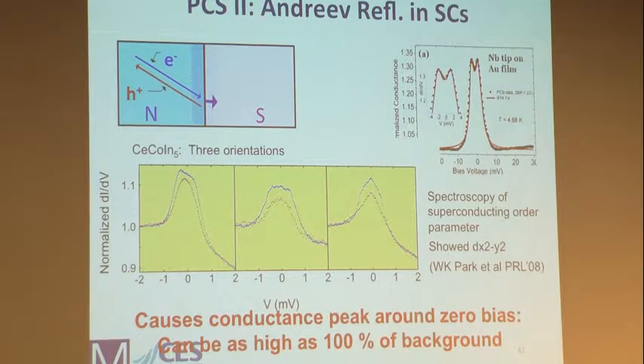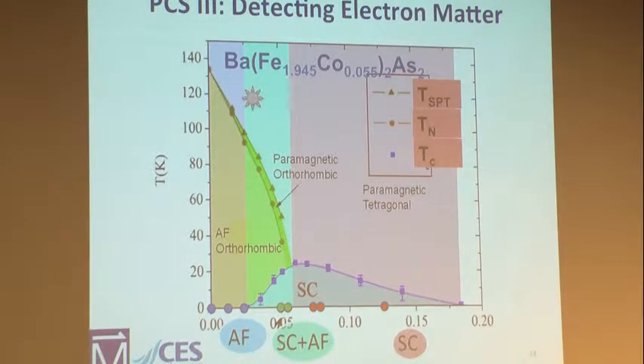And so I'll go into this one now. And I think rather than going to the heavy fermions, I want to talk about the iron-based superconductors. So this one will show how we pick up the electronic nematicity. Here is the most studied of the iron-based high-temperature superconductors: barium iron-2 arsenic-2 with cobalt doping. And that's what we have doped, okay? It's about 23 degrees Tc. Way up here, it's paramagnetic and tetragonal. As you go down in temperature, first you go through a structural phase transition, and then antiferromagnetic, and down here it's antiferromagnetic and orthorhombic. And my student Hamoud Aram, I said, hey, we don't know what's going on in this point contact stuff. See if you can pick up what's going on at these phase transitions here.